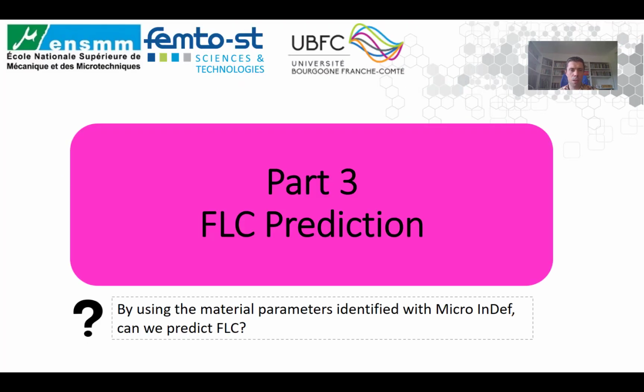So the last part of this presentation is the prediction of the forming limit curve with identified parameters. Within the industrial framework, the concept of formability is necessary to define if a part is manufacturable or not. In macroscale, the forming limit curves are used to serve this purpose. But the question is, is this approach applicable for microscale? And can we obtain a reliable experimental FLC? The second question is, by using the parameters obtained with micro-indef tests, can we have a numerical prediction of the forming limit curve?